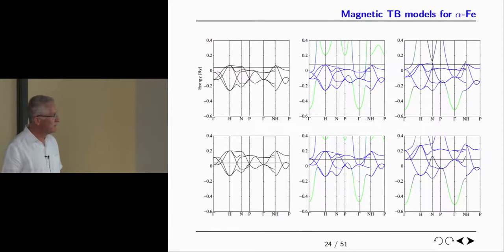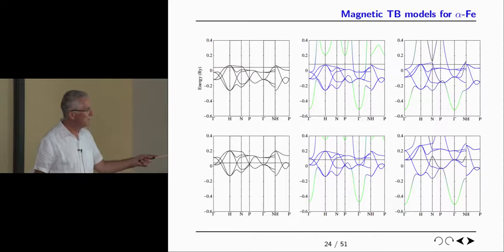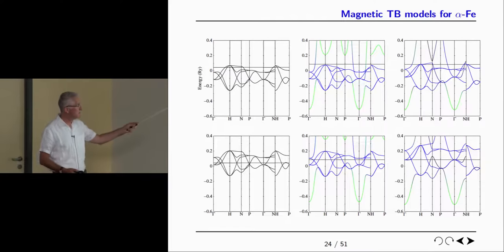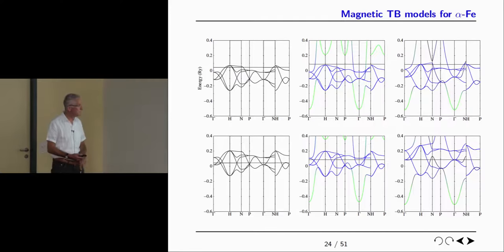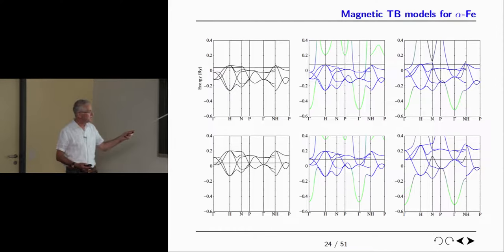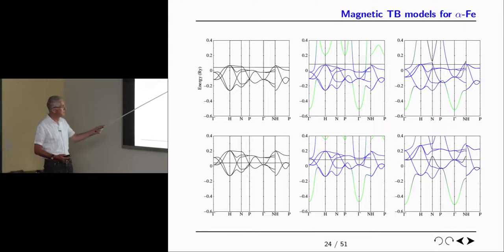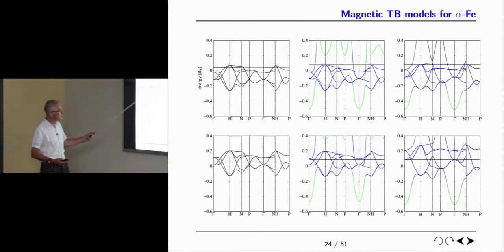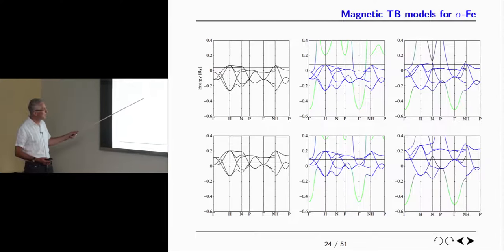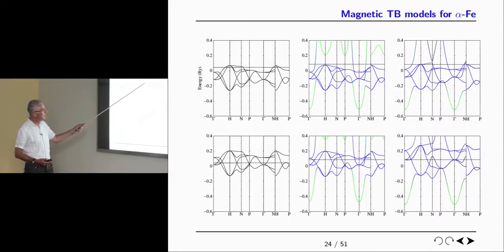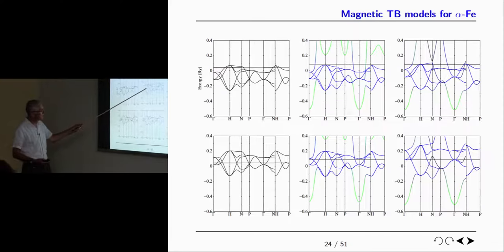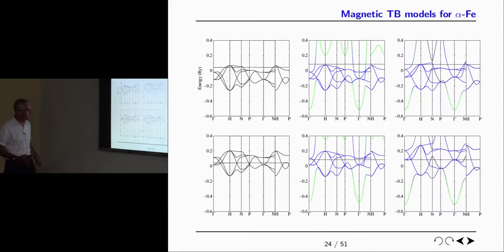These are energy bands. So if only d electrons are used, then one sees a set of d bands. This is the majority and the minority spin channels. And in the case of putting in an additional s electron into the tight binding model, you can see the typical transition metal feature of an s band, which is free electron-like, cosine-like, but as it crosses, it hybridizes and mixes with the d bands to produce a mixture of d and s-like bands, and then at high energies, it reappears as a free electron band again up above the transition metal. Here's the Fermi level, and so this is the majority, and these are the minority spin channels.